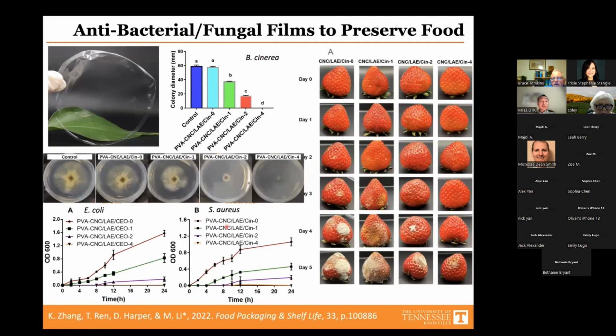Okay, so what do the results look like? This is the film, and we incorporated the emulsion into the PVA film. It's pretty and nice because it's really transparent. Then we determined the antimicrobial activity, and we first tested these films against Botrytis cinerea, which is a common fungus found on grapes or strawberries. We have a control here, which is no film added. And this is the film added, but the film has zero emulsion added. And 1, 2, and 4 mean we added 1, 2, and 4% of the emulsion into this